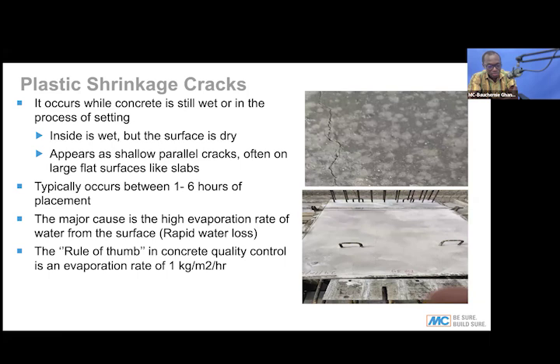So this kind of shrinkage cracks, plastic shrinkage cracks, are mostly seen within the first 1 to 6 hours of the application of the concrete. When you apply the concrete, within the first 1 to 6 hours, you have these defects happening. And as I mentioned, the major cause of it is the high evaporation rate of water from the surface. So when the water leaves the surface and there's no recharge, definitely you have what you call plastic shrinkage.